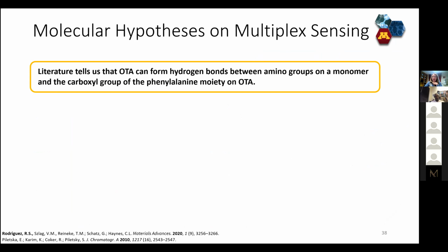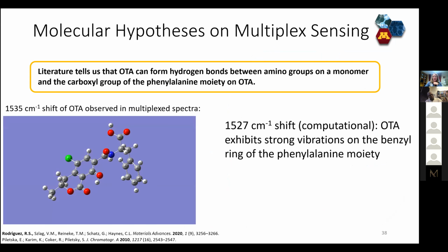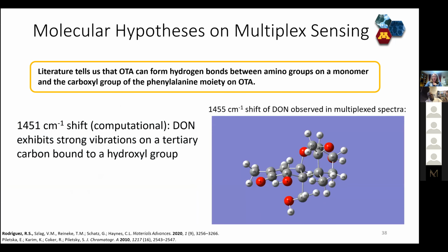So we dug in a little bit to try and understand exactly how the polymer was interacting with the targets, because of course we want to think about optimally designing a polymer that can bind to whatever we like. Literature suggests that the ochratoxin can form hydrogen bonds with the actual monomer unit. And so Becky went through and did calculations, and the band we ended up looking at most to try and quantify ochratoxin was this one at 1527 wave number shift. You can see in the little movie here that this is a vibration happening on the phenylalanine part of this molecule. She did the same analysis for the DON. There we were looking at a shift around 1450 wave numbers, and you can see that this was all about movement on a tertiary carbon in the hydroxyl group of the molecule. Quite a big movement there.